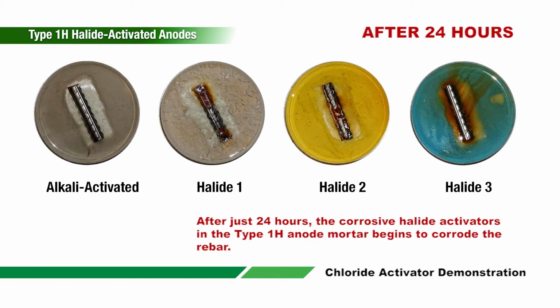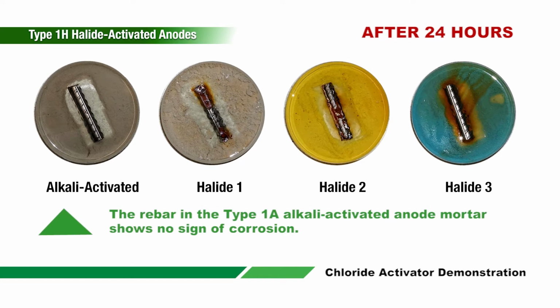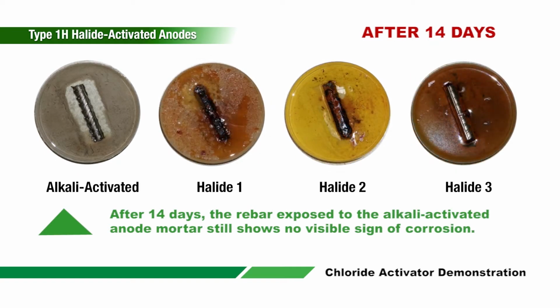After just 24 hours, the corrosive halide activators in the Type 1H mortar begin to corrode the rebar. The rebar in the Type 1A alkali-activated anode mortar shows no sign of corrosion. After 14 days, the rebar exposed to the alkali-activated anode mortar still shows no visible sign of corrosion.